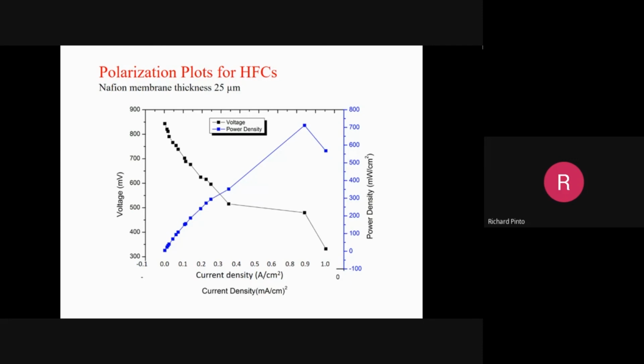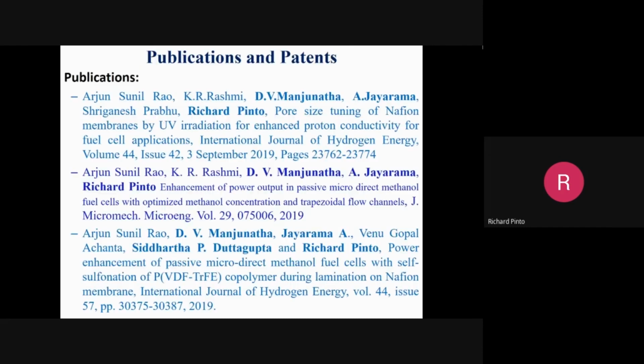this is for 25 micron, which gives better performance. Obviously, internal resistance is down. The reliability issue we have to check, but you got as high as 700 milliwatts per square centimeter, very high power. 700 milliwatts per centimeter square, almost 0.7 watts per square centimeter for the 25 micron membrane. These are all plots for UV exposure.